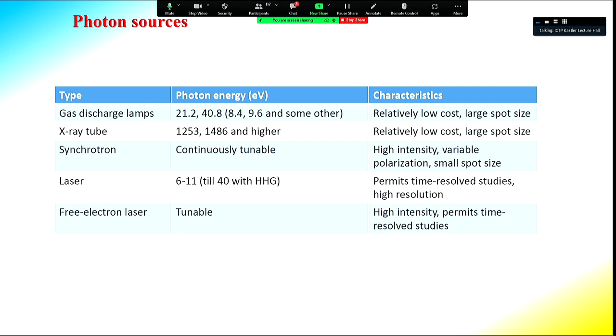For studying the valence band, one normally uses gas discharge lamps that provide typical photon energies, while x-ray tubes are commonly used to study core levels. Synchrotron light is one of the most commonly used techniques to study electronic structure — it provides continuously tunable light over a very broad energy range, high intensity and brilliance, variable polarization, and smaller spot sizes. Laser sources have a limited range of energies but permit time-resolved studies and offer much higher energy resolution. More exotic sources like free-electron lasers are harder to access.